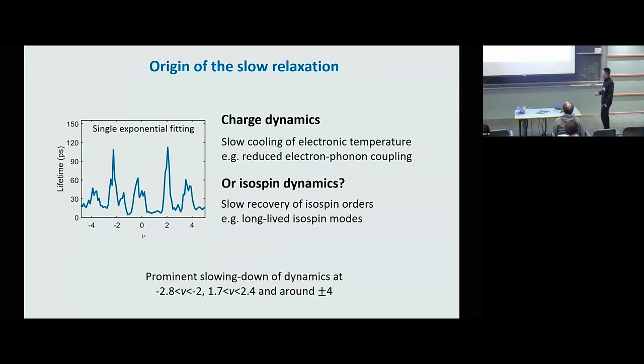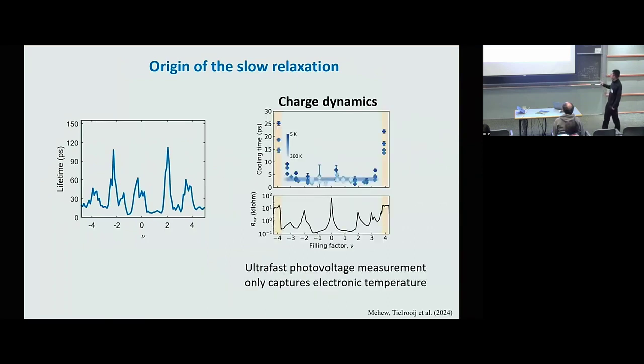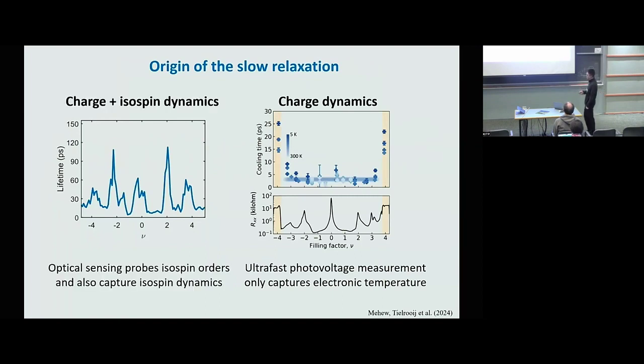Fortunately, we can directly answer this question because there's a previous study which already measured charge dynamics in MATBG. They used the ultrafast photovoltage measurement. We know in graphene, the photovoltage is mainly contributed by the thermoelectric effect. So if you measure the dynamics of the photovoltage, that's directly charge dynamics, and directly tells us how fast the electron cooling is, and there's no information about the isospin degree of freedom. But in our measurement, as we have seen, it's sensitive to isospin orders as well.